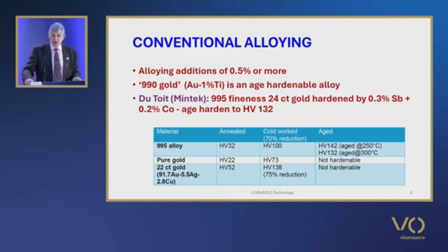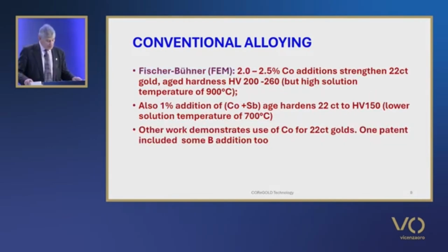And we can argue whether this is conventional or microalloying. My feeling is it's probably the latter. Fischer-Bühner, when he was at FEM, has demonstrated the use of circa 2% to 2.5% cobalt additions to effect significant strengthening of 22 karat gold with aged hardnesses of 200 to 260 Vickers, although this involved a relatively high solution annealing temperature of 900 degrees Celsius. And he also showed that a combination of cobalt and antimony, in total 1%, resulted in a hardness of circa 150 Vickers after aging, but using a lower solution temperature of 700 degrees.